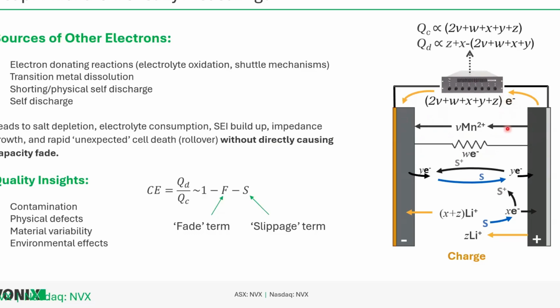We have manganese dissolution. In order to create charge balance in the cell, we actually have to count electrons through this external circuit. And of course, this is going to make this difference between charge and discharge capacity. During discharge, all of these things look like a self-discharge process. In the middle here, I'm showing a reversible shuttle mechanism. This is similar to mechanisms that were published by the Dahn Lab showing that PET tape was contributing to reversible shuttles within cells. And it was detected using UHPC to find these slippage-based mechanisms that persisted months and months into cell cycling.